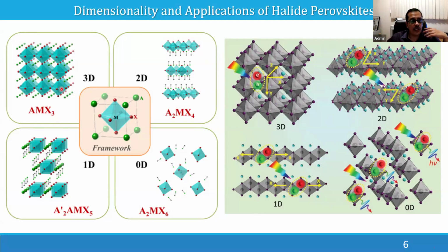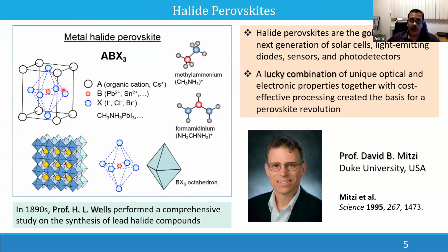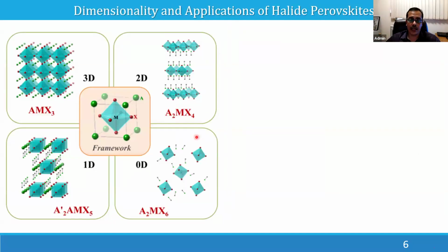But if you increase the size of the organic cation, earlier I discussed we are using simple small organic structures like methylammonium or formamidinium. If you use something slightly bigger, like a benzene with an NH3+, these layers will get separated because the bulky organic group goes into the structure and pushes the inorganic layers. These octahedral structures, the inorganic layers, will be pushed apart to form a 2D structure. The layer forms a two-dimensional mat-like structure.